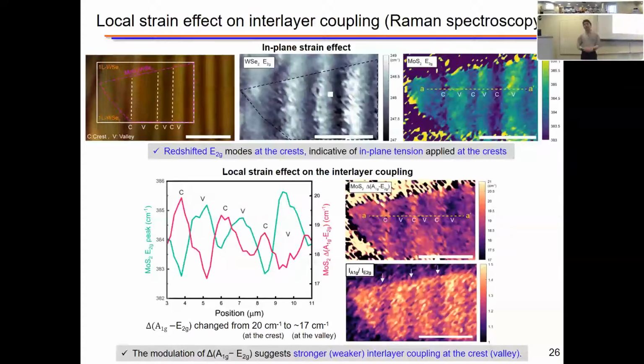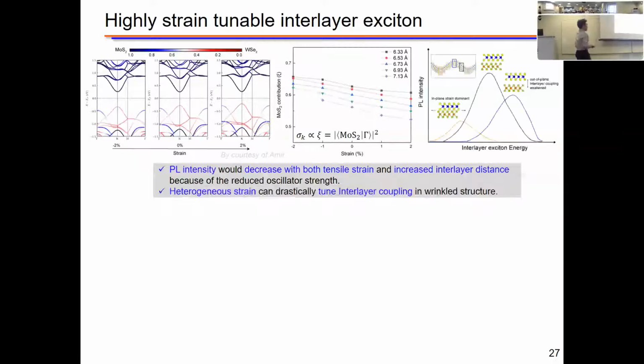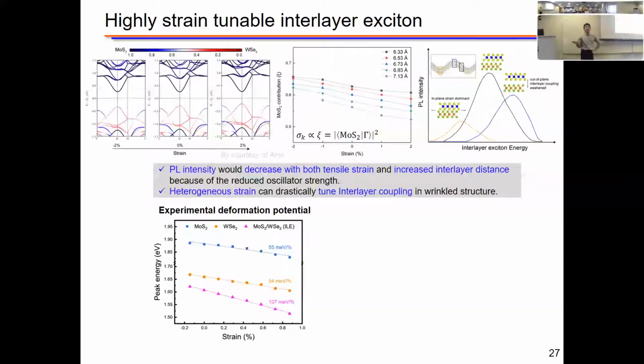You can think of it like a Poisson-like effect. When we pull the material, we expect to see a reduction in the thickness, right? When there's a strong in-plane tension, we expect to see stronger interlayer coupling. So this is just theoretical support. We're very interested in the PL intensity. We correlate that to the oscillator strengths and support that at the valley, interlayer coupling becomes weakened, so there's a reduction in the oscillator strengths that gives us a reduction in PL intensity. However, at the crest, interlayer coupling might be sufficient, but in-plane tension also modulates the band structure, giving us a reduction in the oscillator strengths and resulting in lower PL intensity as well.